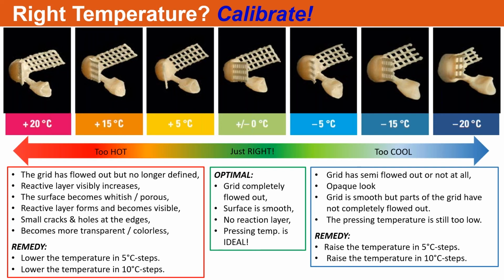There are ways that you can test your pressing process. We have patterns that you can get, for like the saddles of a partial denture, that we recommend that you place on your sprue. You press out something and then make sure that that pattern completely presses out, and then we know we're at the right temperature. If you go too low, it doesn't change the color so much. It does become a little bit more opacious, however, but you won't have the defined pressed margins that you need.